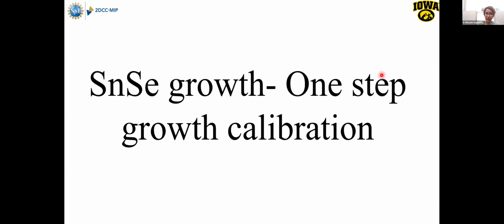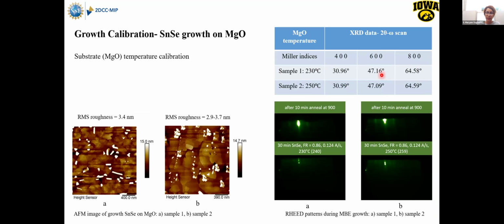So for the tin selenide, we started developing the recipe with one step and two steps. Since this is recipe development, we have lots of results. I just picked some of them. So this is the one where we change the temperature of the sample. And you can see by changing the temperature of the sample, the film quality is getting better, and also the RHEED pattern confirms that.